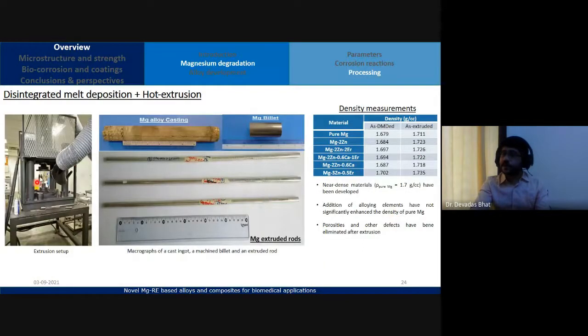So following which we go for extrusion. So this is the extrusion setup that we have used, and this is snippets of how the extruded rod looks like, right? These are few density values. You can see for the as extruded, the values of densities are higher as compared to the as DMD materials.